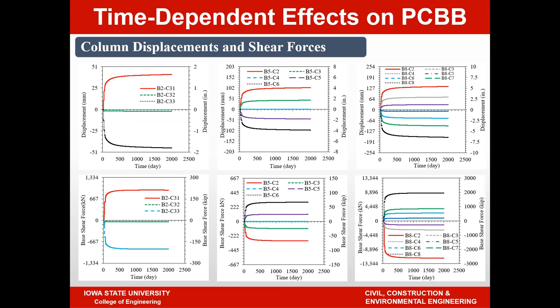So you can see clearly, if you look at the top displacements or base shear forces, these values are not constant between the columns. The extreme columns typically see much larger forces. Again, you can clearly see that as you get closer to the center, some of these columns see very small forces, and therefore they may not even experience cracking as much as you see for the extreme cases, where the cracking may take place in a matter of days.